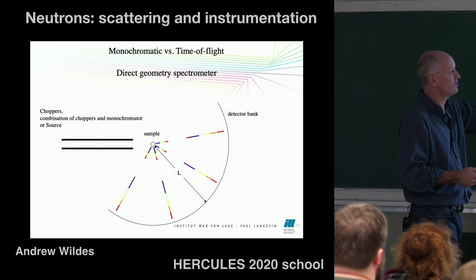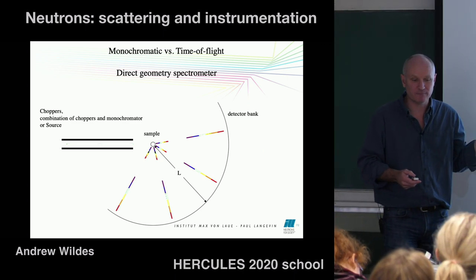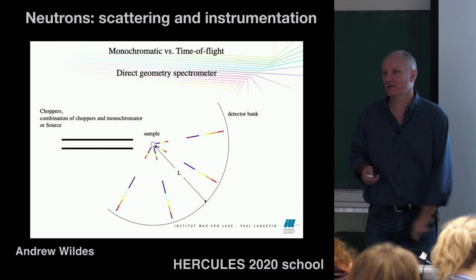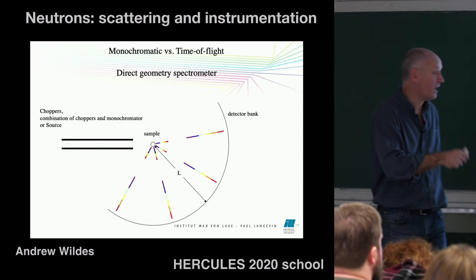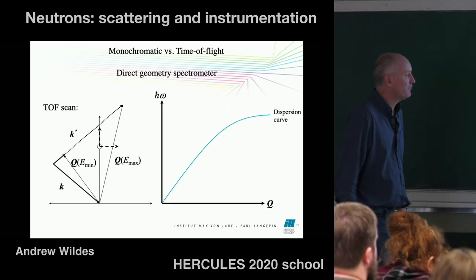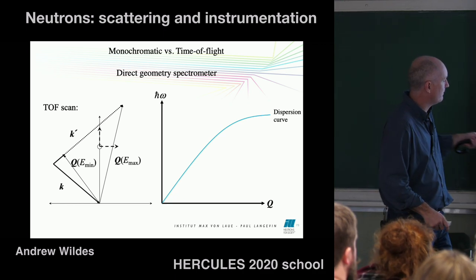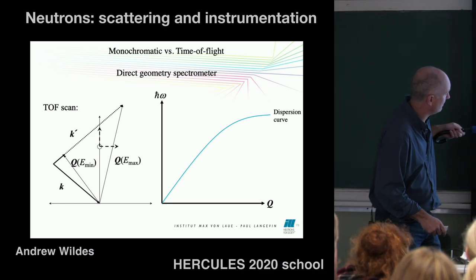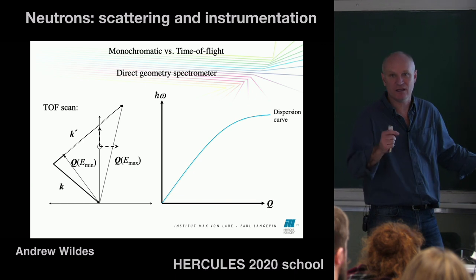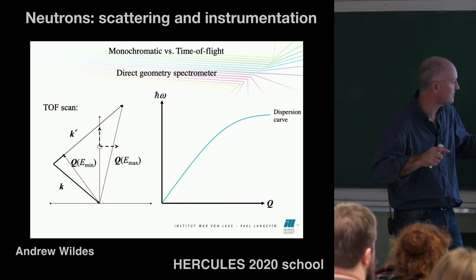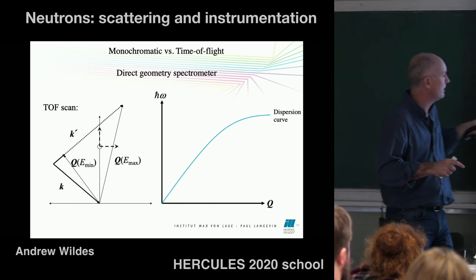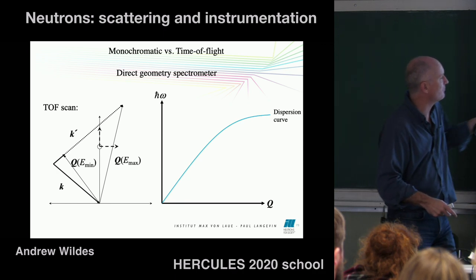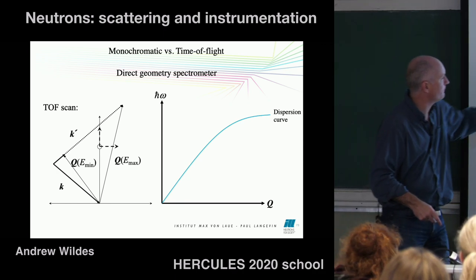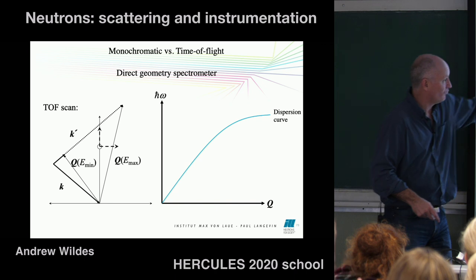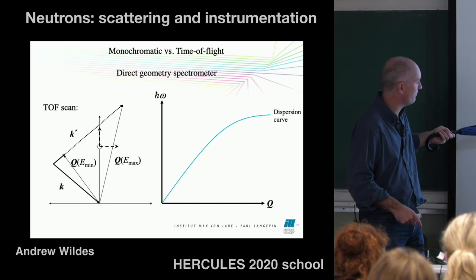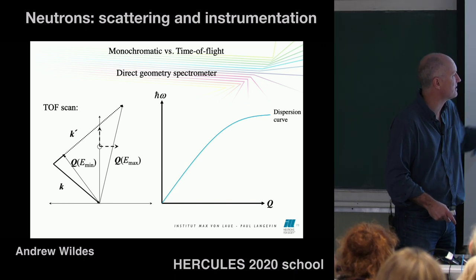So here's the direct geometry spectrometer. You're coming in with a pulsed beam in time, but it's also monochromatic. If you look at the trajectory you're covering there, your initial vector is fixed in length and in orientation. Your final vector is fixed in orientation, but the length changes. And the trajectory that you're following is rather long in Q. You've got to go from a Q energy minimum to a Q energy maximum.